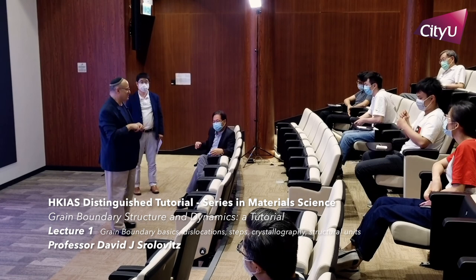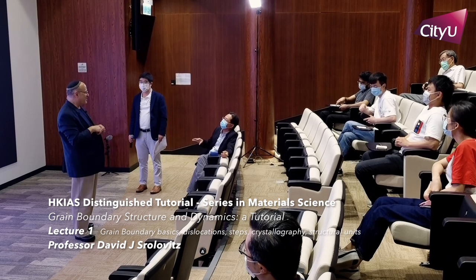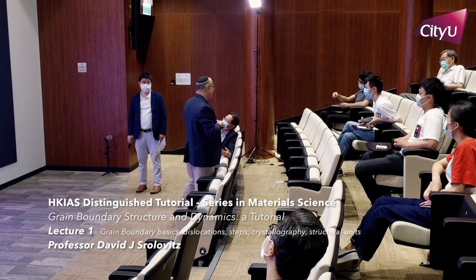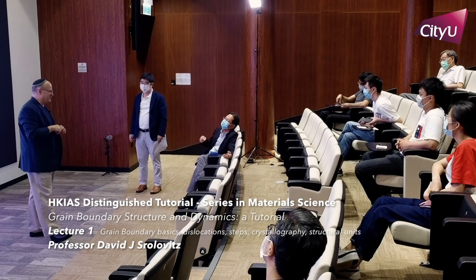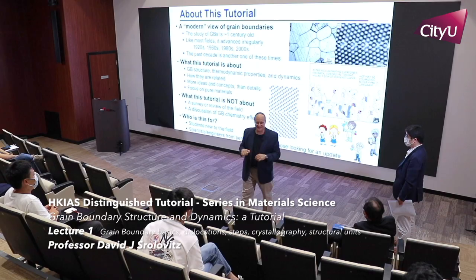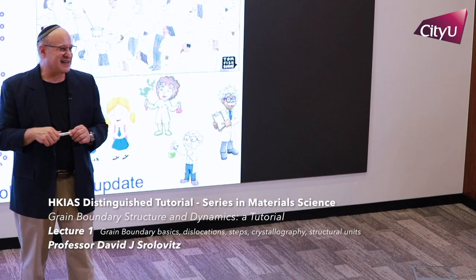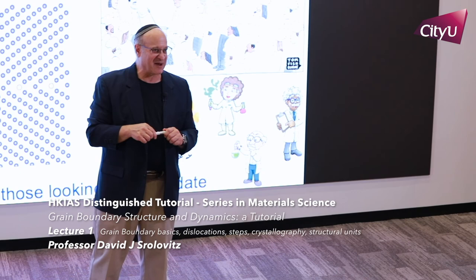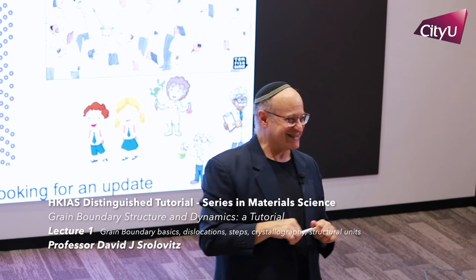The simplest way to make direct comparisons is not in the energy, because measuring grain boundary energy is not a very accurate thing. But structure, if you do high resolution TEM, you can look at the details of the structure and see how that varies. And so that's more where the comparisons will be. I would say that getting grain boundary energies accurately is much more difficult on the experimental side than it is on the calculation side. My view.